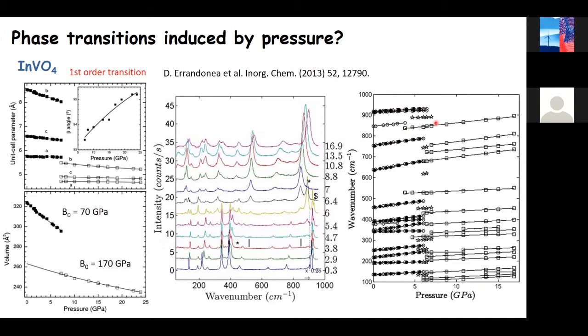In particular, you can see here these modes are related to internal vibration of the vanadate unit. And something I didn't comment yet is that when we have the phase transition, there is an increase in the coordination of vanadium from 4 to 6. That makes the vanadium-oxygen distance elongate a bit in order to accommodate 6 oxygens around vanadium, and therefore the stretching modes will lower their energy. As you can see here, the highest frequency mode is around 900, and in the new phase is clearly below 900.